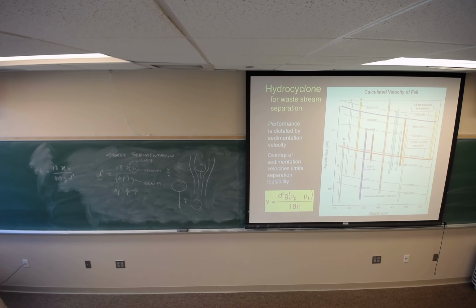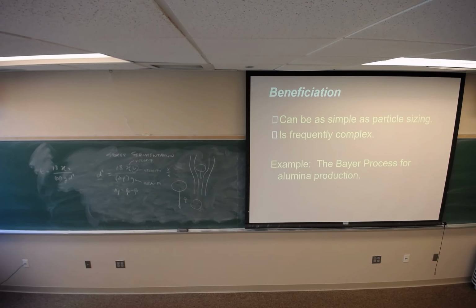So what you're really looking at in this equation is mass. So diameter times density, and you correct for volume, but you just assume spherical, so you can do that calculation easily. You get a mass of the particle. A mass of, say, 0.01 grams made out of one material with high density, if it matches the mass of 0.01 grams of another material with a lower density, they settle at the same velocity. Therefore, I can't separate things out. Good? Okay. So beneficiation processes, as simple as particle sizing, can be quite complex, or froth flotation.